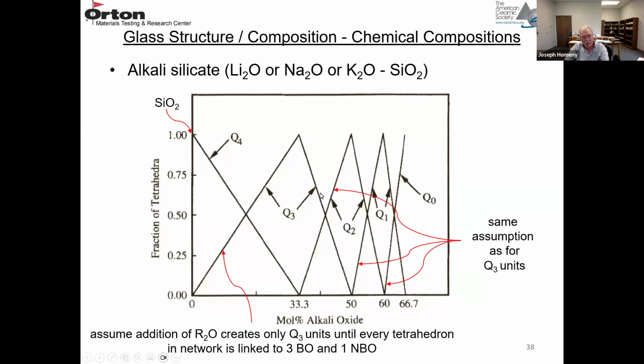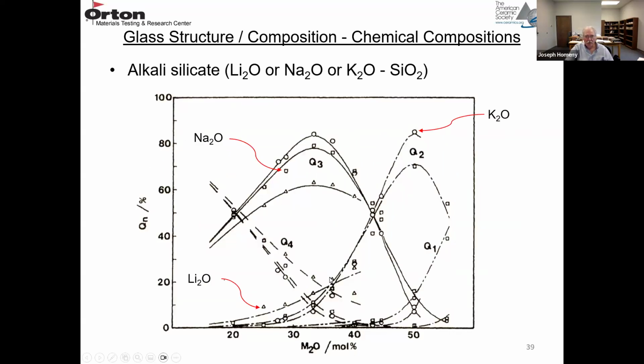This is in theory, and in reality, if you measure this, it basically follows the theory. The lithium is the open triangles, the sodium is the open squares, and the potassium is the open circles. So you can see how these Q3 units form, the Q4 units decrease, the Q2 units increase as the Q3 units decrease, then the Q1 units increase, and the Q2 units decrease. So this actually follows the theory very well.